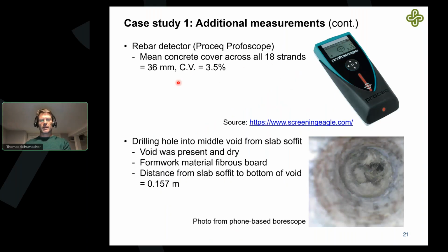The rebar detector, here we used this Profoscope to get about a mean cover of about 36 millimeters for the pre-stressing strands at the bottom. This is showing a photo from inside the duct. I'm looking at the formwork actually. So we drilled from the bottom into that middle void, pushed the camera up, and you can see the formwork material. No water came out. Second indication, confirmation, these voids are not water filled, they're dry. Showed this fibrous board. The measurement from the bottom of the slab to the bottom of the void was about